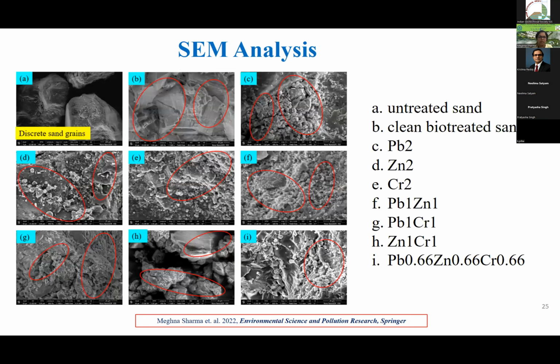And next is SEM analysis. In the scanning electron microscopy also, you can see these discrete sand grains. These are untreated sand grains, and these are the biotreated clean sand. You can see the crystals, and the crystals of contaminated sand. There is a difference. But the calcite precipitation occurred and strength was improved. We can analyze the type of crystal and morphology of the crystal.